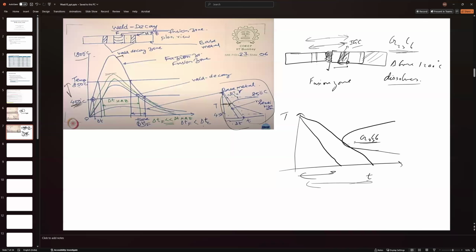So if you take the first case in the fusion zone, what will happen is you're crossing 1200 degrees Celsius. Suppose this is the 1200 degrees Celsius. You're destroying all the carbides. And once you reach 850 degrees Celsius again, and you cool below 450 degrees Celsius, this is the range where your chromium carbide is forming. So you're spending this much time in this zone. So in the weld zone, you spend comparatively less time in the zone, so you don't form any chromium carbide precipitation since the cooling rate is high.